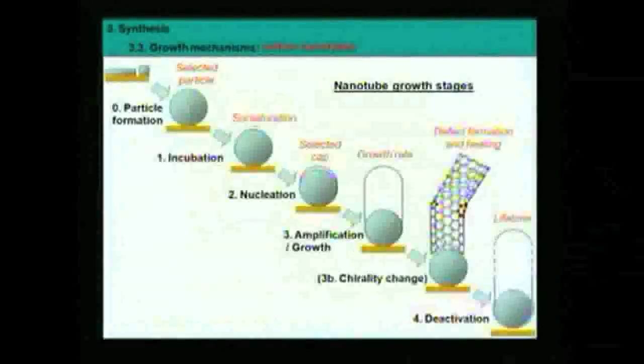The nanoparticle is moving, yes, in another case. Yeah, but you're right, it's important. What we have observed here is that the particle remains at the surface of the support. The tube grows above the particle. The tube does not grow between the particle and substrate. This is a special case. So this is something else we learn. Okay, there are other things we can learn, and from that we should propose a mechanism.